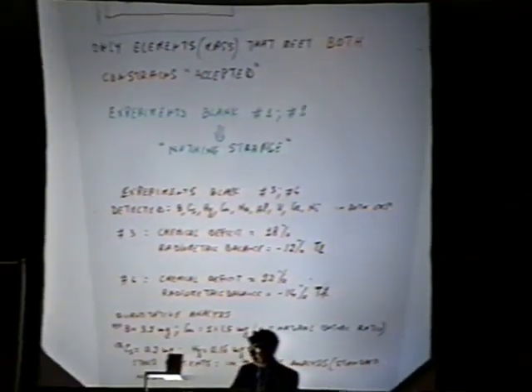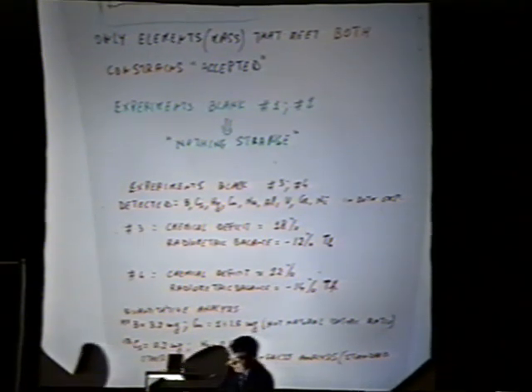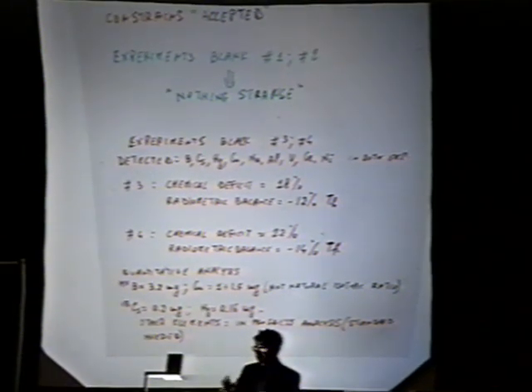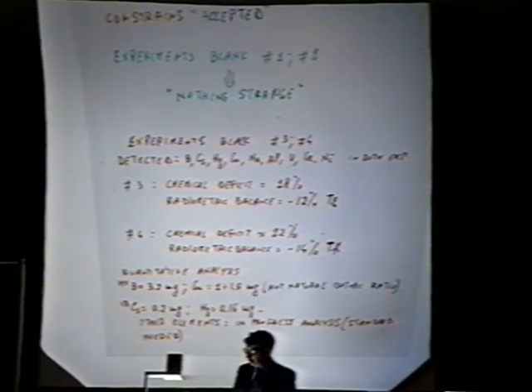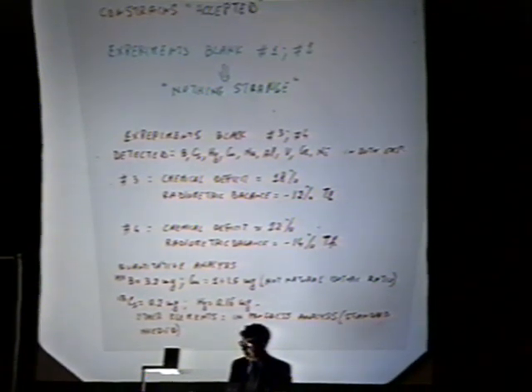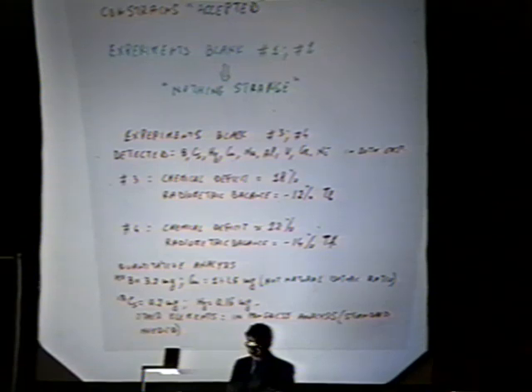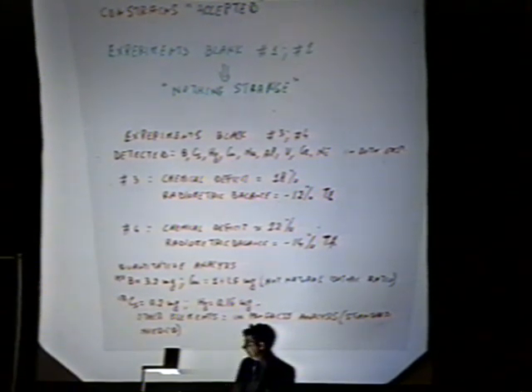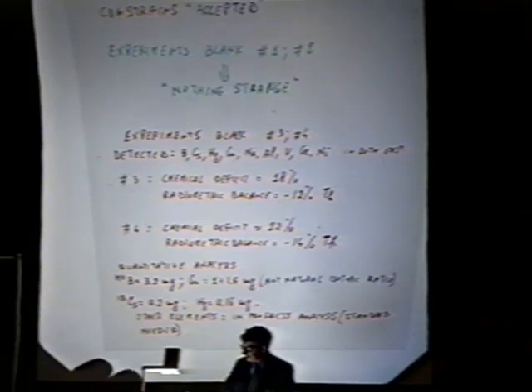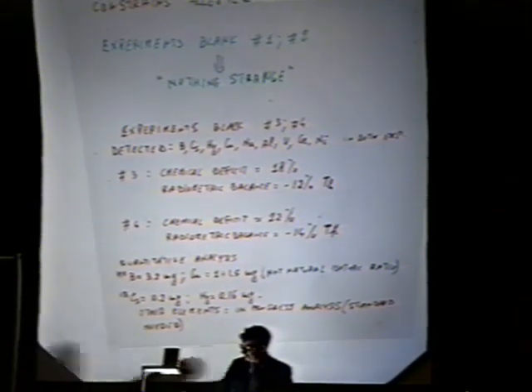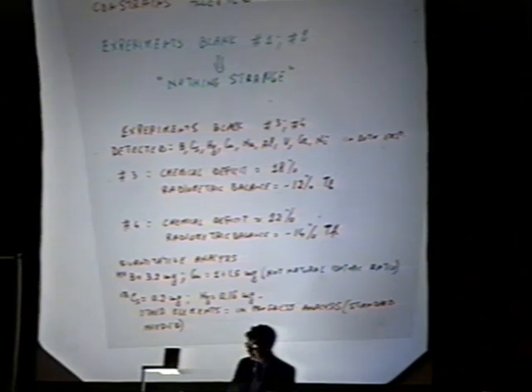So in the blank experiment, we detected almost nothing strange. In the thorium experiments, the result was more or less similar, and we got boron, cesium, mercury, and copper, and a lot of other elements. We still have to analyze them from the quantitative point of view. The chemical deficit was about 28% for experiment number 3, and the radiometric about 12%.